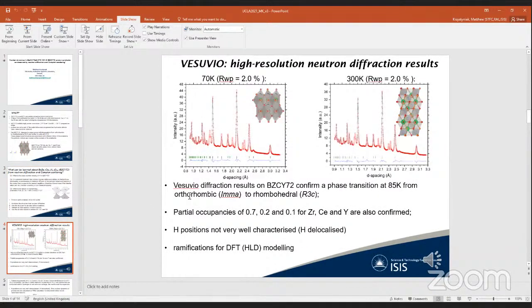So the question about the structure has been addressed by analyzing the neutron diffraction, and it has been confirmed that there is a phase transition as reported in the literature at 85 Kelvin from orthorhombic to rhombohedral structure. Partial occupancies of metals in this framework have been also confirmed. And the problem with hydrogen was that even using neutron diffraction, hydrogen positions were not very well characterized. So it has to be assumed in further studies that we take the structure solved and we don't place partial coordinates of hydrogen.